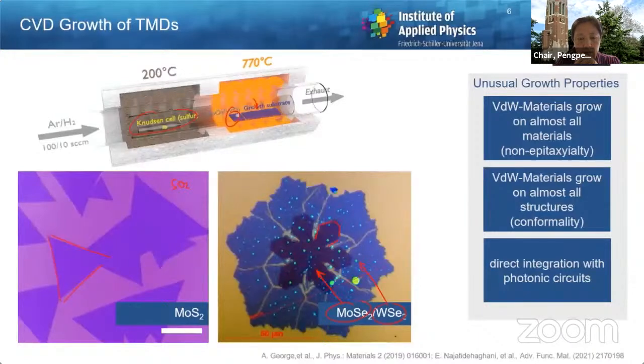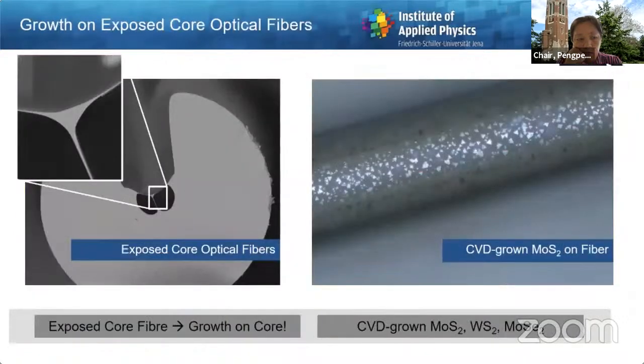What's maybe even more profound is that you can grow them also on non-planar structures. So they grow both non-epitaxially and also conformally. And therefore, this approach lends itself very nicely to direct integration with photonic circuits. And the simplest photonic circuit you can think about, I guess, is an optical fiber. So this is exactly what we did.